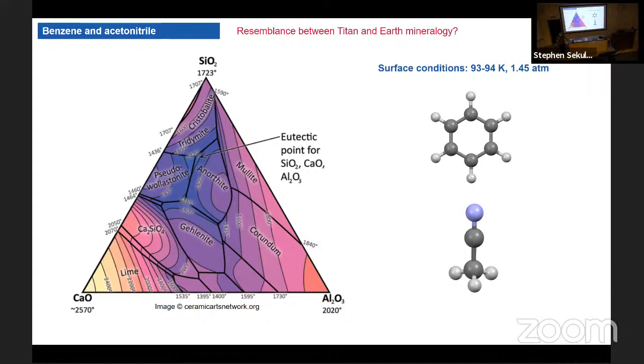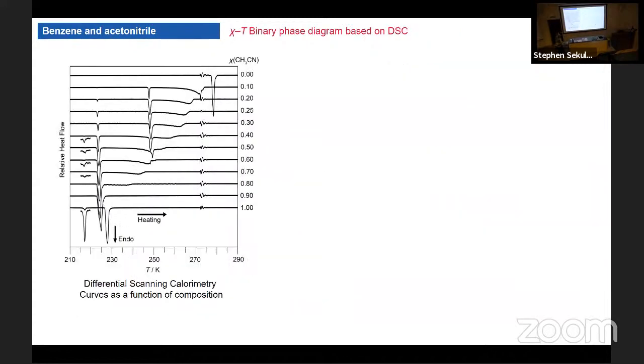First of all, we can look at crystallization, but that's not a good idea because crystallization can be a stochastic event that may be determined by even impurity. If you have a seed of crystal, you will have crystallization. So it's not thermodynamically driven. On the other side, melting is. Melting is a very thermodynamical event. That's the reason why we decided to look at the melting peaks, the endothermic peaks of mixtures of acetonitrile